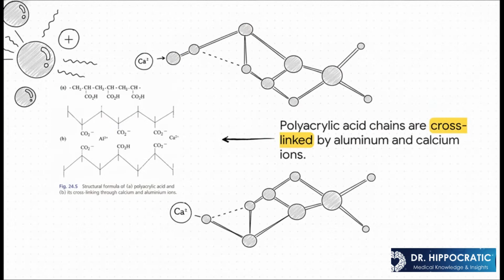And this is how it all clicks together. When you mix the powder and liquid, the acid starts to dissolve the surface of the glass particles. This releases those calcium and aluminum ions. These ions then act like tiny bridges, grabbing onto different polyacid chains and linking them all together. This creates a strong, tangled, cross-linked structure, and that's your final solid cement.